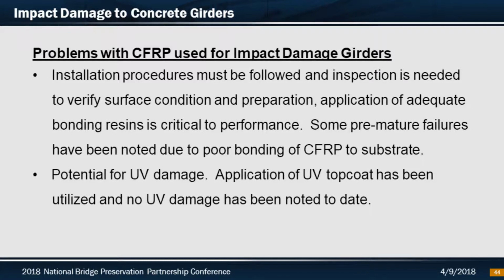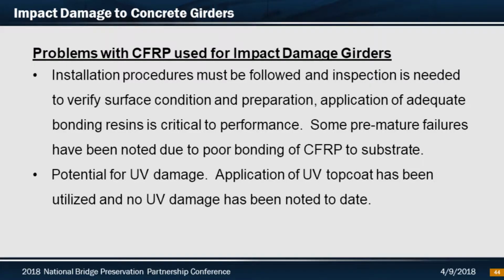Seems like we had very good performance. I guess once you put it up there and it doesn't get hit, you don't know if it's doing anything. I think recently we've had a couple of impacts, or at least one, where we noticed an entire section of wrap fall off the bottom of the beam, and we're associating it to surface prep and application of bonding resin. So I think inspection and proper construction are critical. Other than that particular location, I don't know that we've found anything different. But there is potential for UV damage, probably more likely on the glass fibers. The carbon fibers are pretty tolerant, but with the UV top coat, we haven't noticed anything to date.